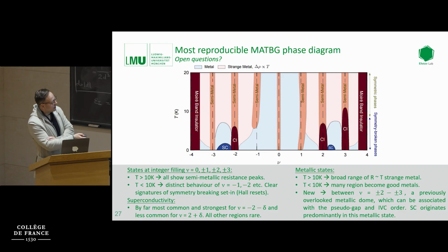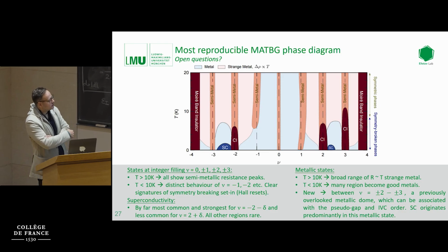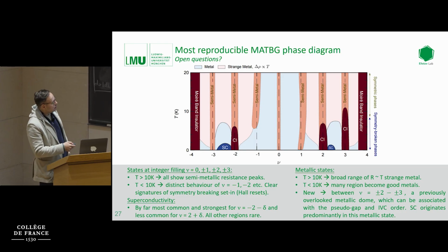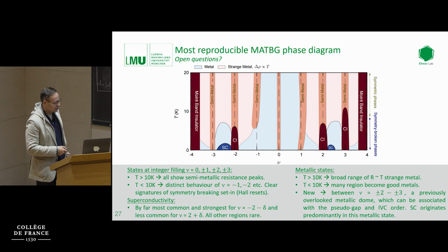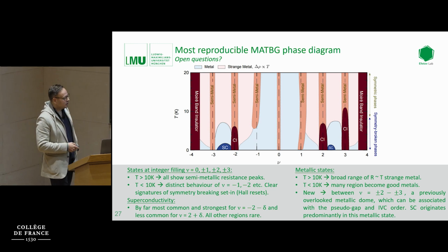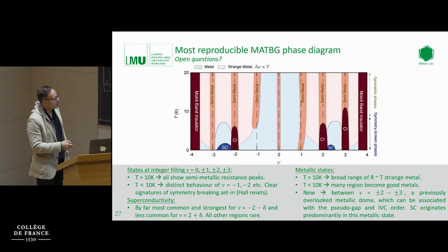So typically below 10 Kelvin is basically the temperature scale of our J. As I said, Coulomb contribution is one thing, but then of course there's exchange interaction. So below 10 Kelvin, J, I think, takes over, and then you have a lot of phase transitions. So the semi-metal here turns into a correlated insulator. Potentially this is due to some sort of ordering of the F electrons at low temperatures.